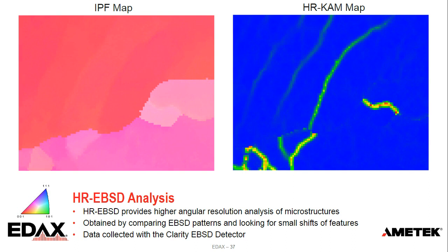From this, you can see the orientation map. There are some slight color changes in this top grain as far as variations. And when we do this HR KAM map, you can see how we start to very clearly resolve where some of those cell walls are present.